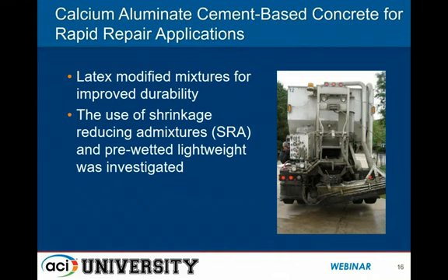So what was done, particularly in the Illinois Tollway, they wanted to identify mixtures that would give us the opening strength that was necessary without having to prescribe the exact mixture, but then also using a few techniques to try to mitigate cracking and also give us some long-term durability enhancements.